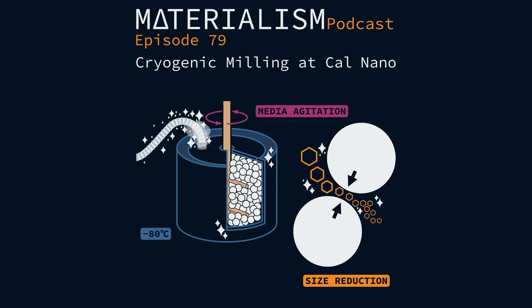Picture, if you've ever seen at Home Depot when you mix your own paint, there's a little mixer, or an immersion blender. This is basically an immersion blender, right? You take this, you dip it into the material, which is going to have your ceramic particles plus the media, and it's going to mix it. Now, obviously, you're not relying on the blade of the mixer chopping it. You're still relying on the ceramic particles colliding, but you're agitating that with a large mixer, basically.